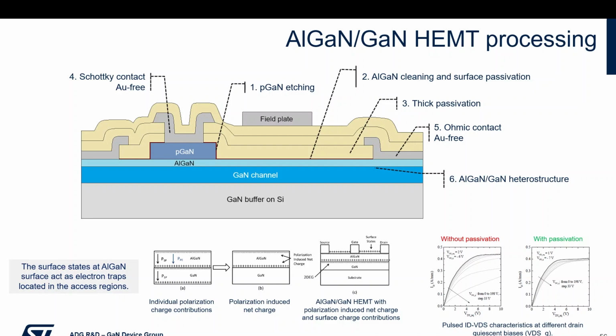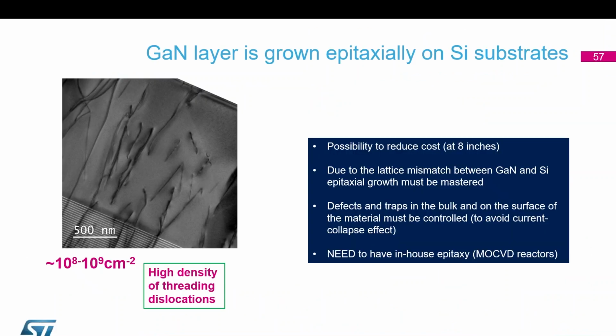The third point is the fact that gallium nitride is not able to sustain a very high temperature process. So be careful about the processes that you use in your ohmic contact, in your processing, if you try to activate dopant, because otherwise you have decomposition of the material. Say above 800 degrees with RTA, it's not possible to go, which is completely different from what happens with silicon and silicon carbide, where in the case of silicon carbide you have dopant activation at 1,700 degrees, for example. Having said that, I'm going to conclude.